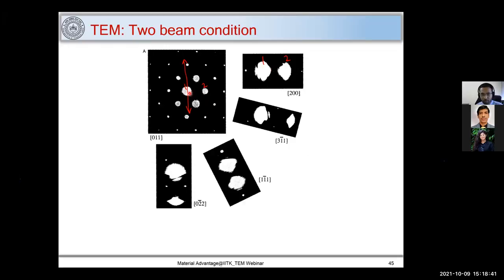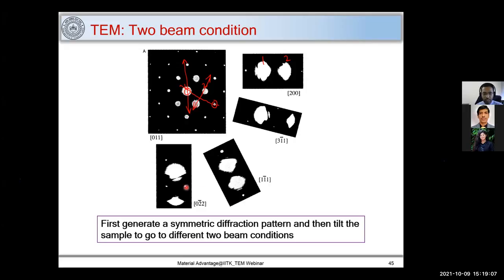Similarly, if I want this spot and this spot brighter, I move with the Kikuchi line. Let me mark here also. So let's say I want only these two spots, this and this spot, to be brighter. So I will have a Kikuchi line in this direction. So I move along this Kikuchi line to make these spots brighter. Similarly, you can excite different HKLs just by choosing a proper Kikuchi line. So here the idea is to get a symmetric diffraction pattern and move along a proper Kikuchi line to get these spots.